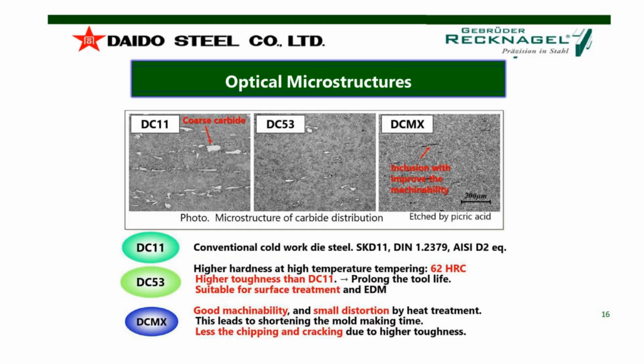It is very important to take a look at the microstructure of DCMX. This picture shows us the microstructure of three grades. On the left side, you can see the D2 grade. The name DC11 is an internal name from Daido Steel. It's the original 1.2379 D2. And you can see in the picture the linings of the coarse carbides. You can see the very big coarse carbides, and this is always a problem with D2 grade.